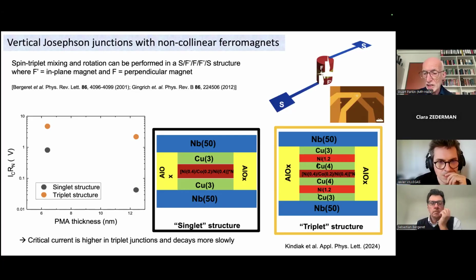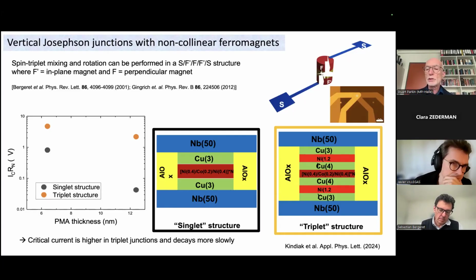On the right-hand side, we build a more complicated structure where we have the same nickel-cobalt multilayer in the middle, separated by copper from now a nickel layer. Here it's 1.2 nanometers thick. And there's a nickel layer above and below the perpendicularly magnetized cobalt-nickel multilayer. In this case, the nickel layer has a moment which is parallel to its plane. In other words, this one has no perpendicular magnetic anisotropy. So the nickel magnetization is actually orthogonal to the nickel-cobalt magnetization.